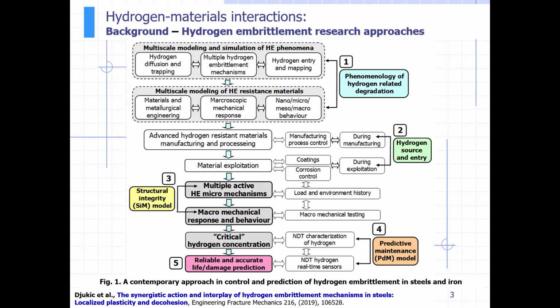And we proposed in 2015 a structure integrity model based on multiple active hydrogen embrittlement micro mechanisms, based on measuring and following the change of hydrogen concentration in material, based on critical hydrogen concentration. And we are still working on a so-called unified predictive structure integrity model for prediction of behavior of material exposed to various hydrogen damage mechanisms.